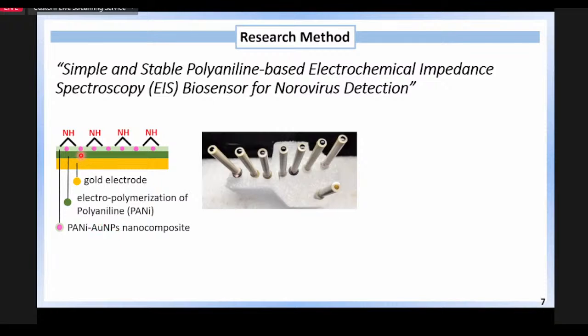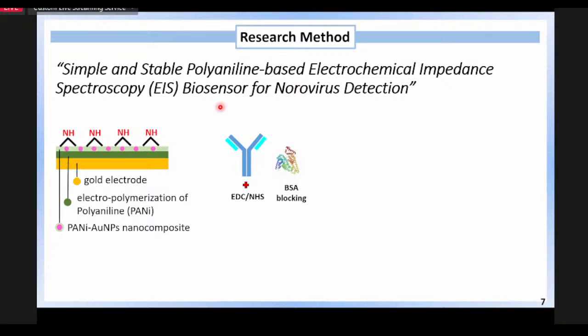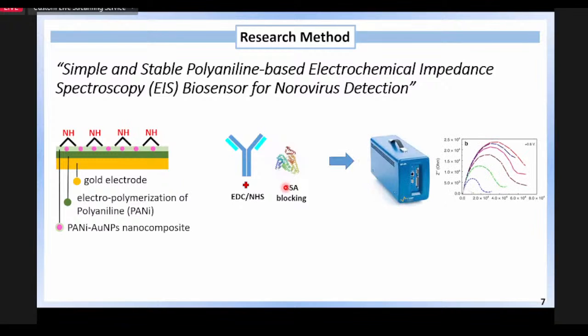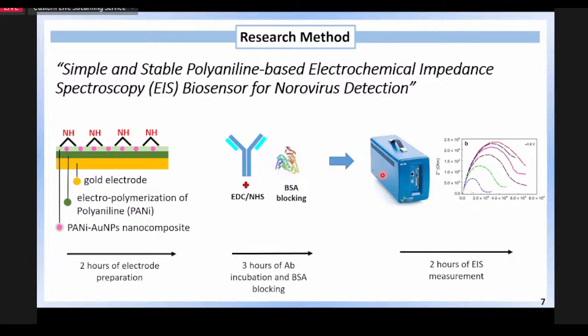The polyaniline has a secondary amine, NH, to which we can later attach the antibody by activating the carboxylic acid group in the antibody with EDC-NHS. Then we block the empty space to minimize unspecific interaction. Then we measure the EIS response with this EIS machine. And in total, this is the illustration of how long the detection takes.